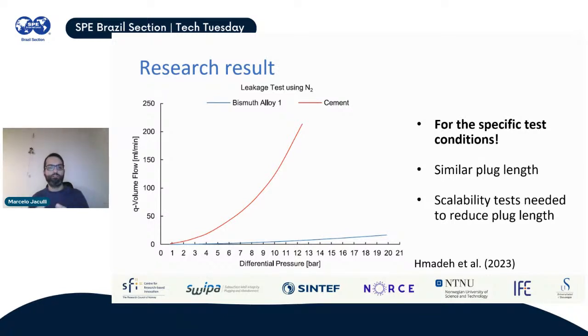But this is going to hold true for that particular condition. And then it's up to us to study how we scale this in terms of reducing the plug length. For example, if we are comparing two plugs which have similar plug lengths, that's good. Bismuth is going to behave better, but it's not necessarily the best solution, because we actually want to reduce the bismuth plug length. And when we reduce the plug length, then it might be more comparable with cement. So that's something you need to investigate further. But the results that we saw from the very beginning, both from the lab and from the field applications that were done by AkerBP, show that bismuth has a lot of potential in terms of reducing leakage rates. So that's the whole motivation behind pursuing this technology.